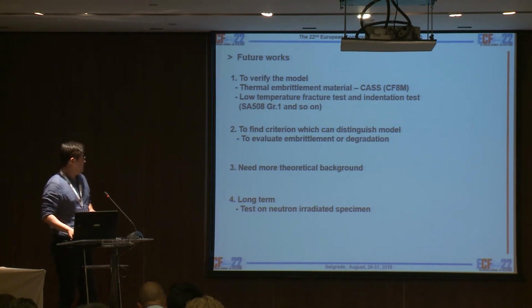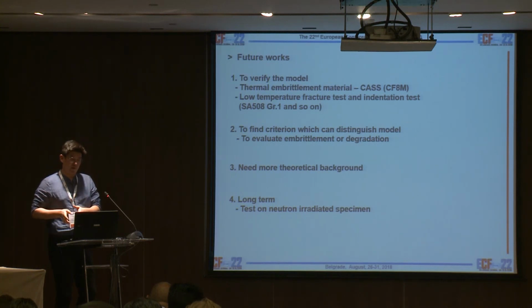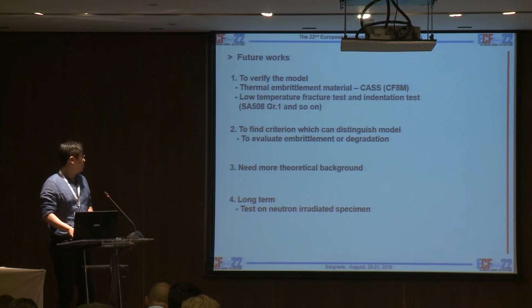And also, instrumented indentation test is actually a non-destructive method, so it is really hard to match with the fracture toughness value. And sometimes it doesn't make sense, I think. So we need more theoretical background. And as a long-term project, we have to test on neutron irradiated surveillance specimens.